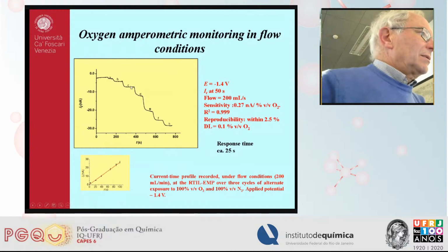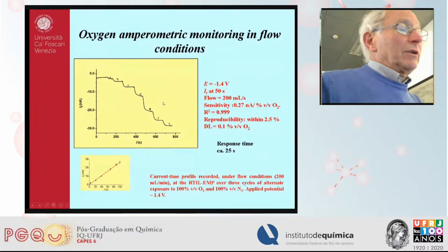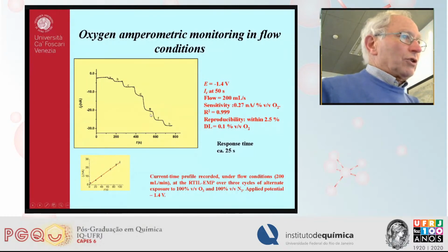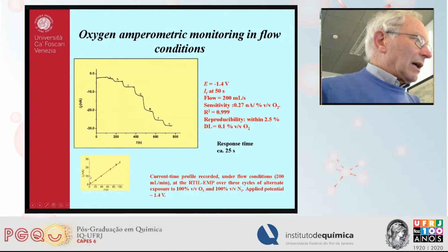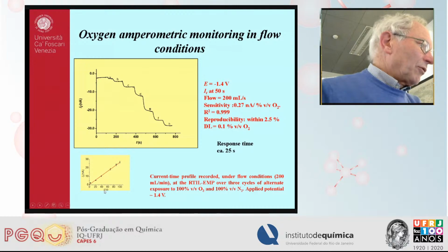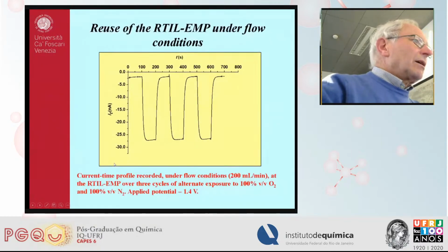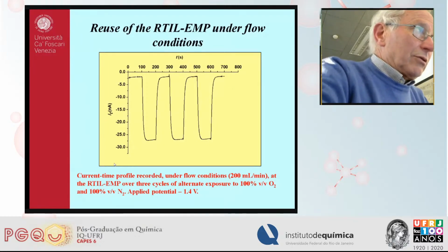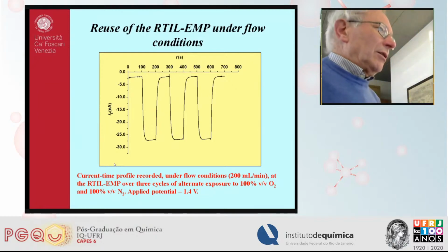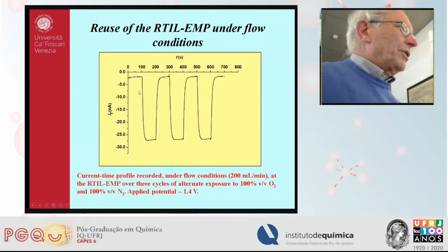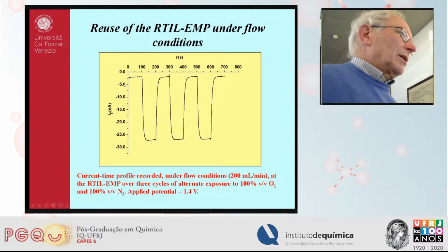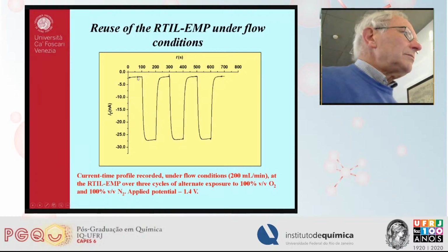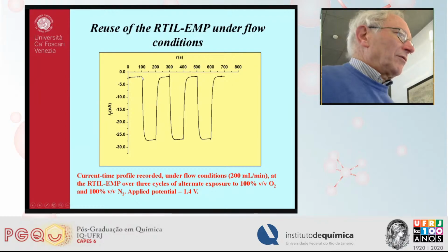And these are the signals we obtain while varying, in flow condition, the percentage of oxygen in the mixtures. And again, the limiting current against the concentration, here it's not time, it's wrong here, it's percentage of oxygen, provides a good linear trend. To prove that this sensor can be used several times, we made several steps like those shown here, which means we obtain a current against time profile in the absence of oxygen, then by sending a constant amount of oxygen,